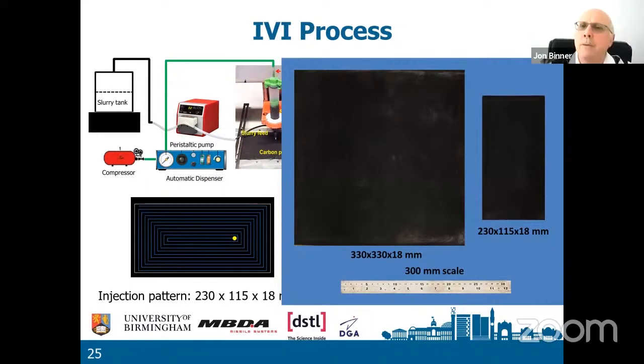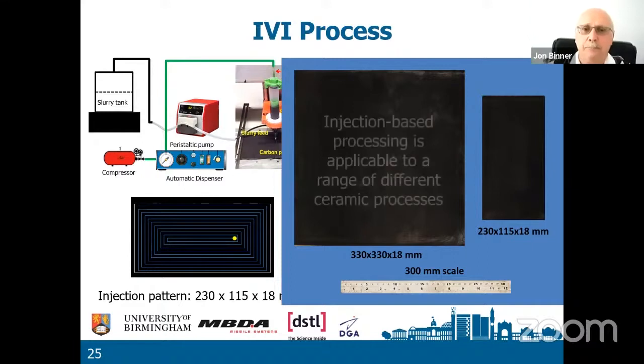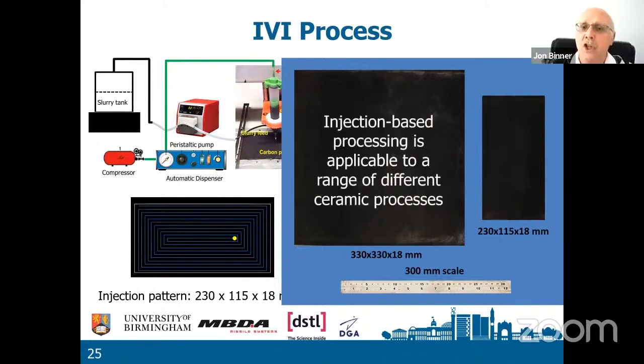Hopefully, you can see that the black is not absolutely uniform. So in the smaller sample, the black is pretty uniform. In the larger sample, hopefully you can see in the top right-hand corner and in the bottom right-hand corner, it's a slightly different shade of black. It's a bit lighter gray. That's where it hadn't completely impregnated it. But nevertheless, that is part of the learning curve, and we can now produce samples that are almost any size, any thickness, and we can get a very homogeneous powder dispersion within them with this technique. And of course, this whole concept of injection-based processing is applicable to far more than just making ceramic matrix composites.